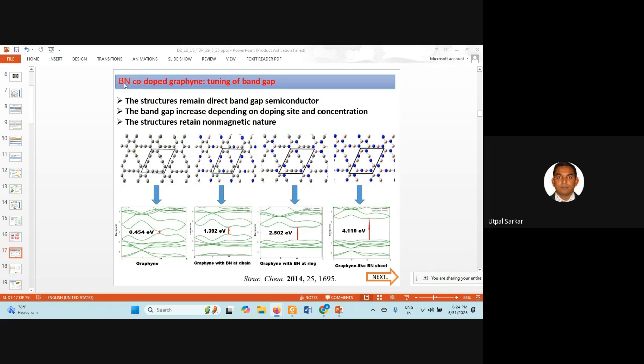When we dope graphene by BN, there are three possibilities. One, we can dope at the ring site. Ring means hexagonal ring. We can dope, and here we have done it. And you can dope BN in the chain site also. So here we have done it, and you can dope BN throughout the system here. Okay, and then how the band gap changes. You see here when it is doped at the chain site, the band gap is 1.39. However, when doped in the ring site, it is 2.5, and when all these carbon atoms are replaced by BN, it is 4.1 electron volt, a huge band gap. Okay, so this material is basically an insulator, you see.